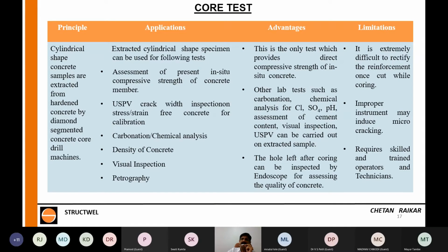And other laboratory tests can be done: chemical analysis, ultrasonic, you can do UPV, ultrasonic pulse velocity, on concrete core samples also. You can do carbonation, chemical analysis, you can know the density of site concrete. You can actually do visual inspection of site concrete, you can do petrography, that is microscopic analysis of concrete. You can use core test for RCPT also, rapid chloride permeability test.